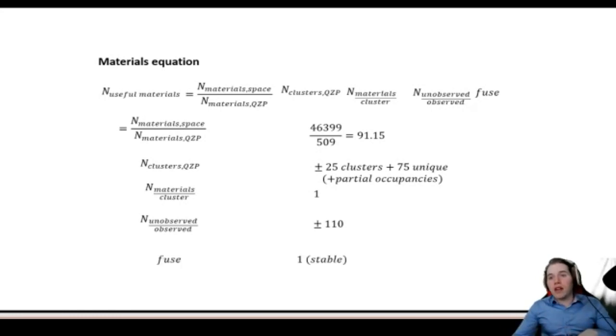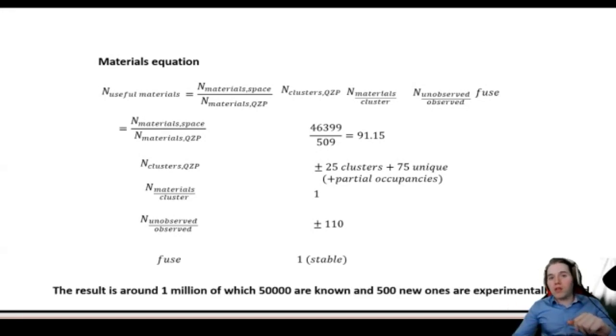So this means that if we say the useful ones, or all of them, the ones that are stable, there should still be about 1 million of these materials in this total material space, of which 50,000 are known and only 500 are added each year. And this is just for quaternary materials. So there are many, many more materials left to find. And this is important because if this was not the case, then we would have to modify existing materials by, for instance, adding small impurities of other elements. All right. So there is plenty left to find.